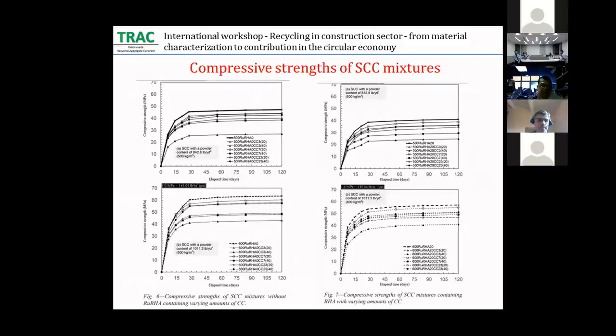For the test of compressive strength, the average compressive strength results of the self-compacting concrete with and without calcium carbonate can be seen throughout 120 days of curing. It can be seen that all self-compacting concrete mixtures exhibit a similar trend in the development of compressive strength, which means that their compressive strength continuously develops throughout the curing time. However, the self-compacting concrete samples mixed with calcium carbonate and rice husk ash have lower compressive strength than those of the controlled self-compacting concrete.